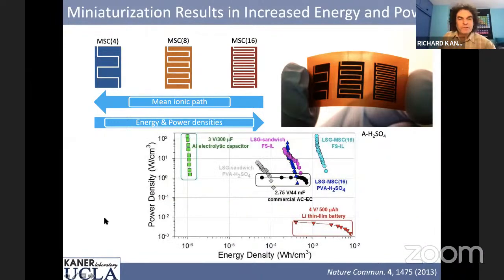You can then put this on a Ragone plot. And so what we're doing here is we're plotting power density in watts per cubic centimeter versus energy in watt hours per cubic centimeter. And here's an aluminum electrolytic capacitor. It has very high power. And here's our laser scribe graphene. And if we use an ionic liquid, we can get power certainly equivalent to an aluminum electrolytic capacitor. So these are very high power devices.